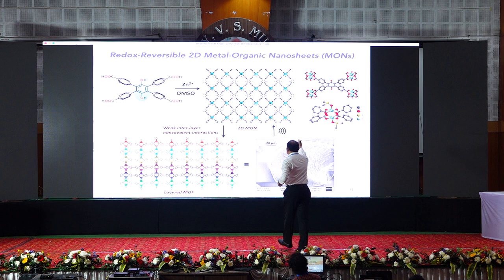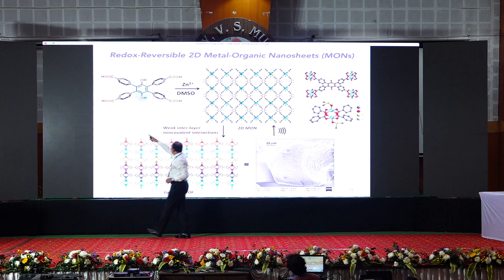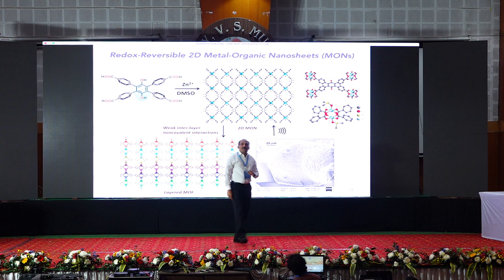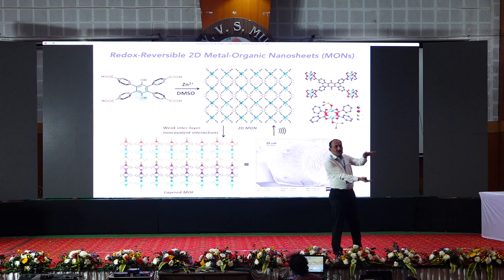a 2D nanosheet. And again, because there is a concavity in between the two rings, and there is a concavity in here, and you can see the porosity here. You're talking about a porous 2D material. And if you have a porous 2D material, of course, what you get hold of is a material where the layers are stuck to each other. Now we want to liberate these layers.